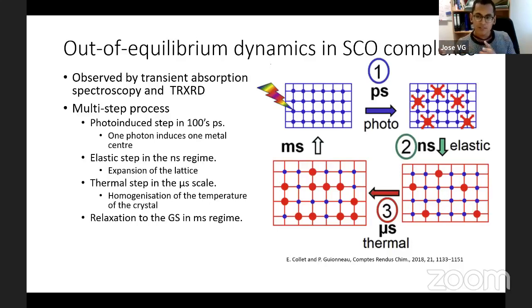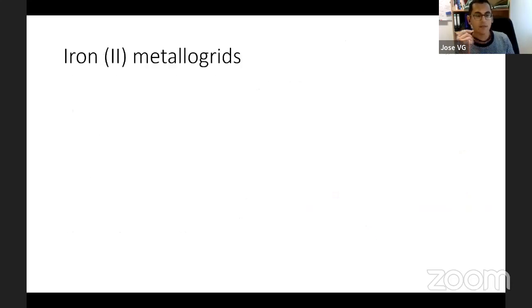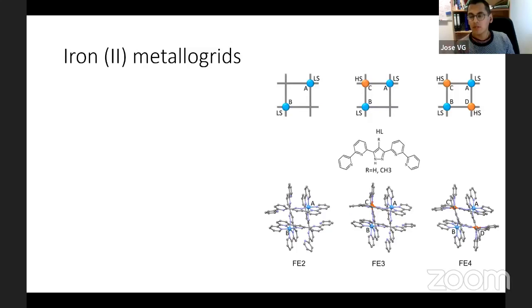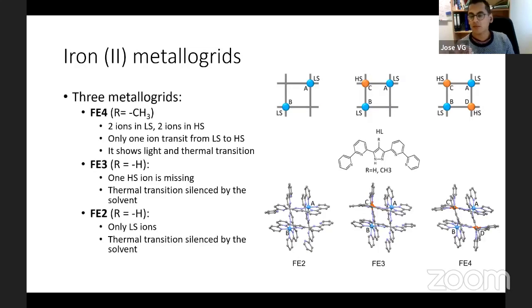In all these steps, there is usually a change. We can actually detect the change from the low spin to the high spin using photocrystallography because of the structural change, because of the bond length expansion. In monometallic materials, there is a curious thing. Regardless of the step, you have only one structural change. However, in our case, we didn't analyze monometallic materials.